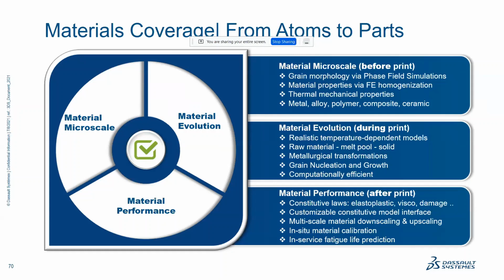So the part performance after the print is done through representation of the mechanical properties as a temperature dependent behavior. Say any material which is at a higher temperature is going to be softer. So taking that as a relationship between temperature and material, you can represent the properties of say the Young's modulus or the plasticity as a function of temperature, which will be represented internally by the solver, which takes into account the stiffness as a function of the temperature of the part at any location. So in situ, we can calibrate the material and estimate the fatigue life in a more accurate manner.